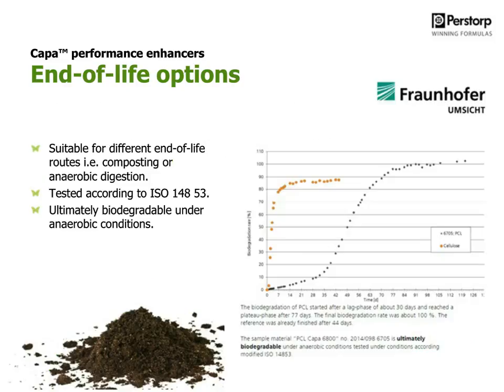The latest studies that we did last year together with Fraunhofer Umsicht also showed that this polymer is biodegradable under anaerobic digestion or anaerobic environment, which means there is no access to oxygen. And this is especially interesting if you're collecting organic waste and they are sorted into a biogas production facility.